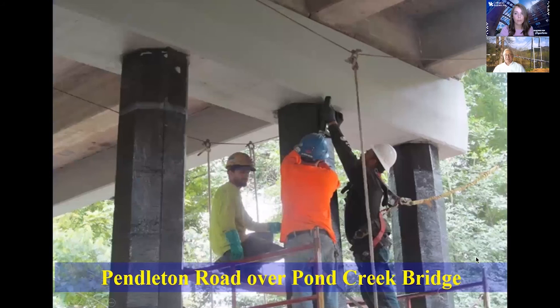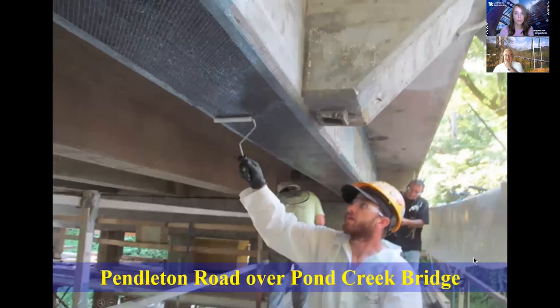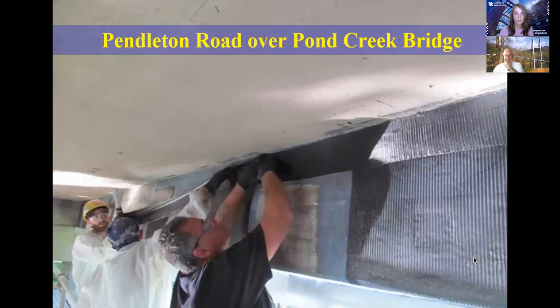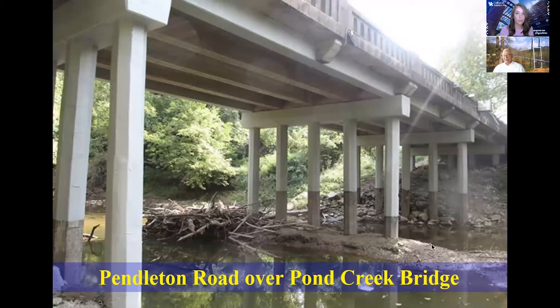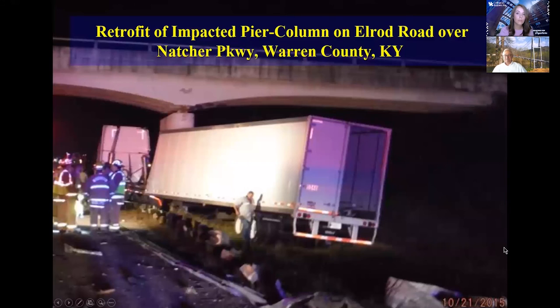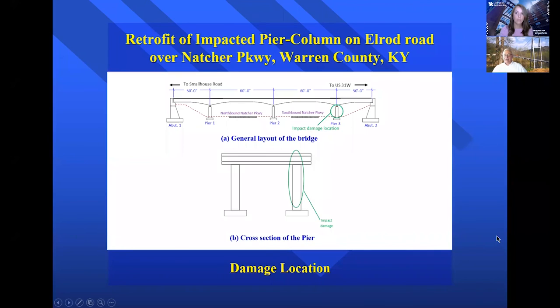This is another bridge in Louisville that was heavily damaged. Again, when it finished, the substructure of this bridge was much stronger than it was originally built. This is in Warren County, where this pier was impacted by a truck, and the damage looked minimal to the pier, but it was really heavily cracked, but major cracks occurred on the pier cap.